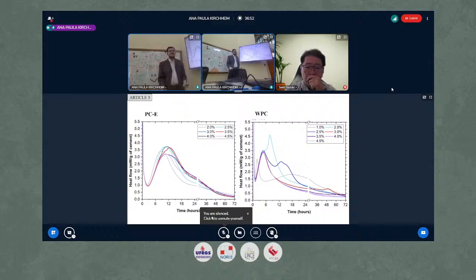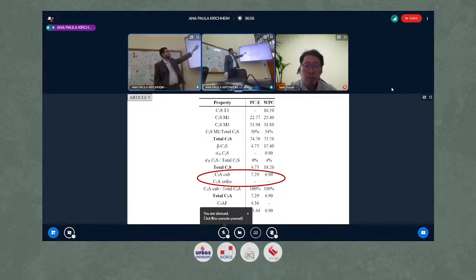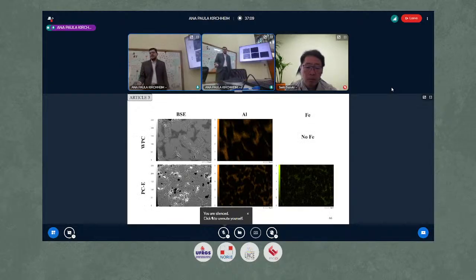Or it could be C3A polymorphism. Both are on theory, as shown here. In fact, PCE has a slightly higher C3A content. So it's neither the C3A content nor the C3A polymorphism that can explain this higher aluminate peak. So our hypothesis that needs further investigation to be confirmed is the absence of iron, the absence of C4AF.